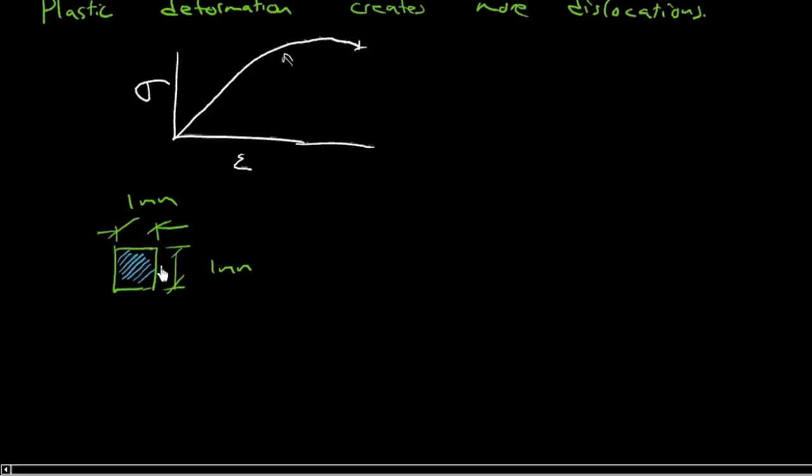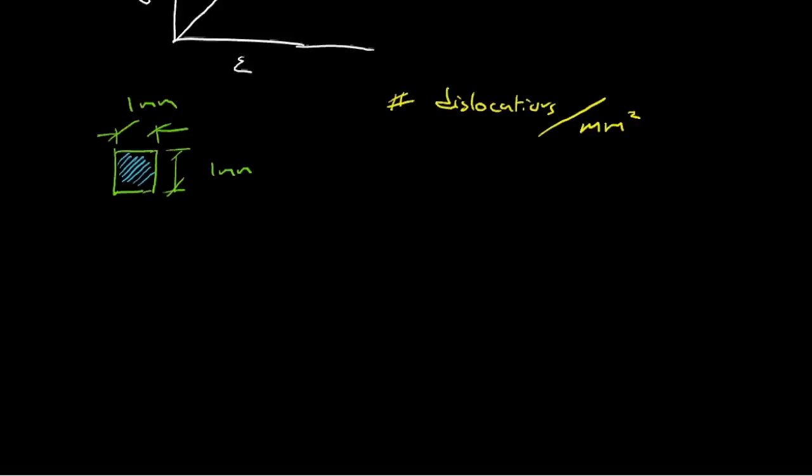Then you cut from a piece of metal. And then what you do is you go through, and you look at that in a really high-powered microscope, and you count the number of dislocations running through that square millimeter. So then you count the number of dislocation lines per square millimeter. You find, I mean, how many do you think? What kind of number? You got a mole of atoms is 10 to the 23. So you should be thinking it's probably a fairly good size number. But these are imperfections in the crystal. So what are we looking at? Well, if you have on the low end, you can have about 1,000, 10 to the 3 dislocations,